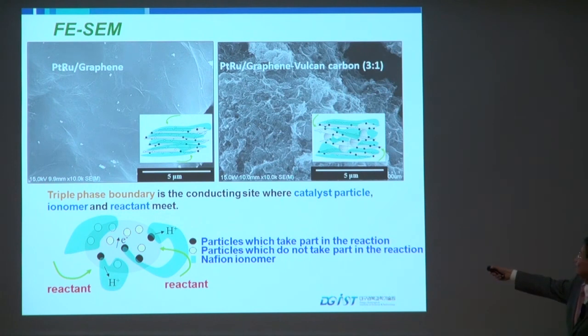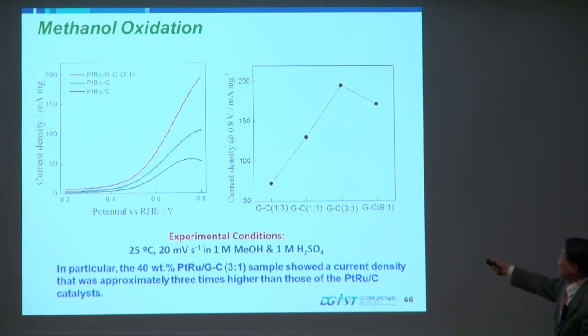When you prepare graphene platinum ruthenium, or graphene, it is very smooth, and not much platinum ruthenium can be anchored on top of graphene. So theoretically it should look like this, but actually it isn't. We imagine this, and we do not know, because there is no way we can observe how they are located. But anyway, methanol oxidation with the different graphene and carbon mixtures has a higher activity. So definitely we can separate some of these graphene nanosheets, and 3:1 turned out to be the optimum.